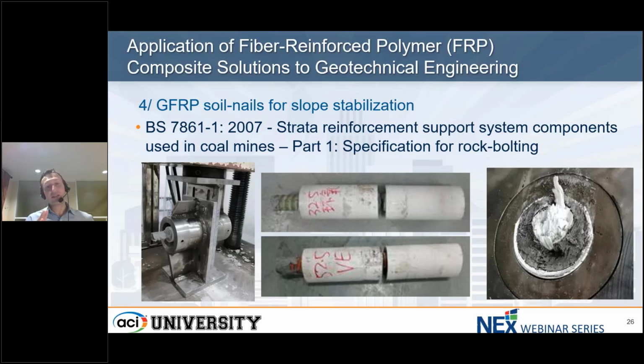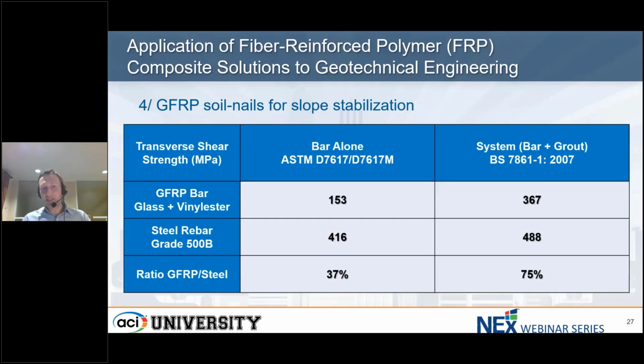This is the test of a simulated borehole. So the sample is tested with its surrounding material. It can be cement grout, it can be resin grout, but we don't test the bar alone. We do test with surrounding material. And we've run the same test, again, with a GFRP bar and of course with the steel bar as well as a reference point. So let me present it in this way.